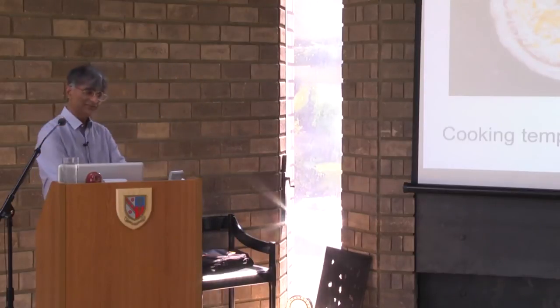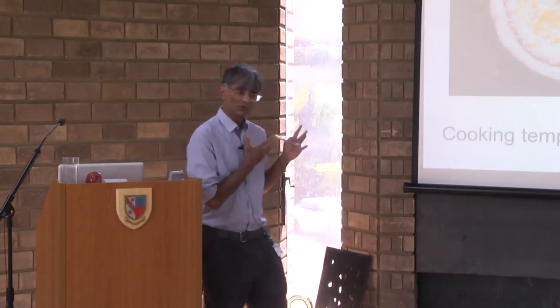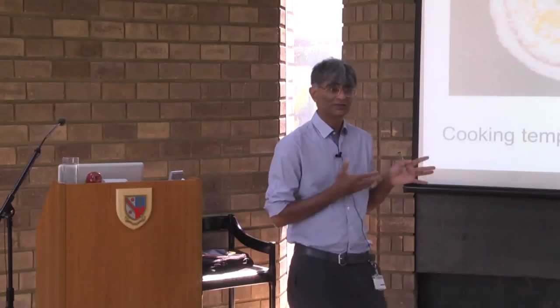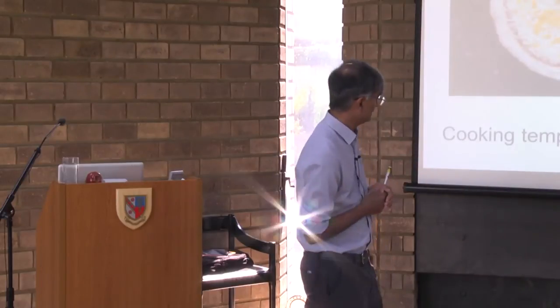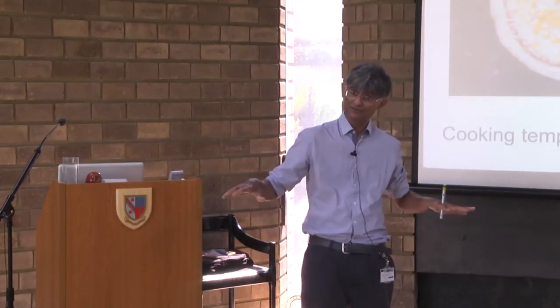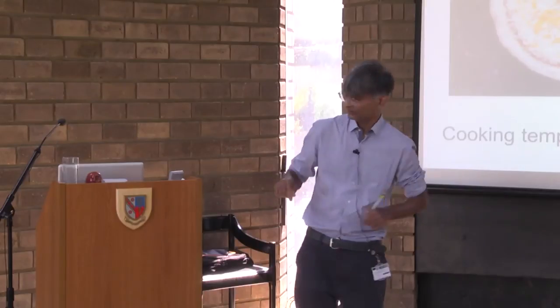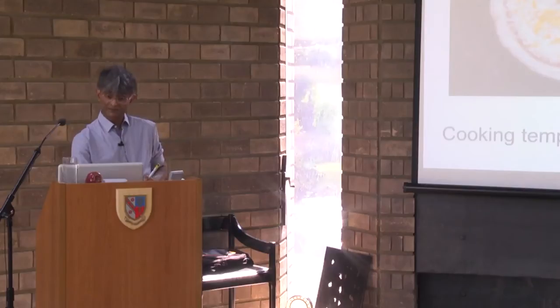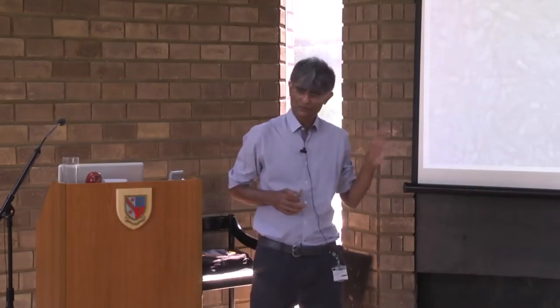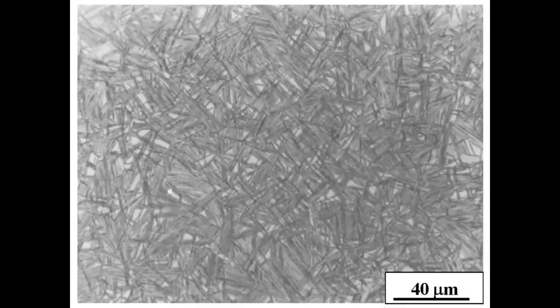So this is extraordinary because there is no other material which is cooked at a temperature of 200 degrees centigrade. It takes 10 days to generate this set of crystals. So basically, you put it into an oven and leave it there for 10 days. And this is the structure that you obtain. And if you showed this to a metallurgist, this is 40 micrometers, so there's nothing exciting about it.